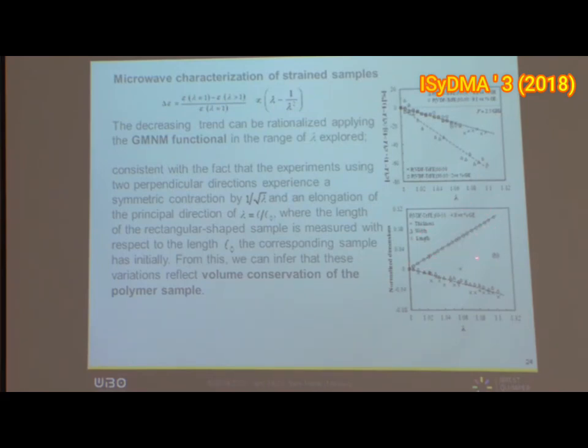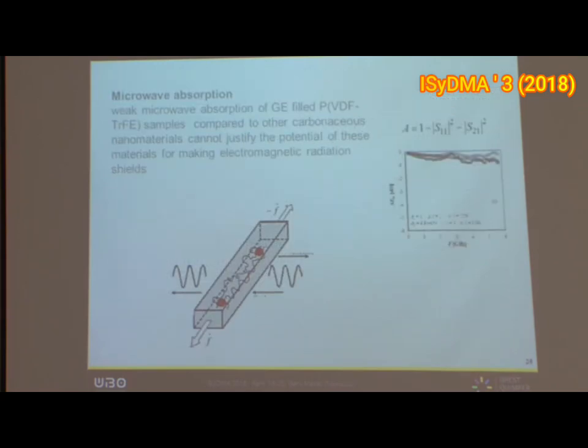The distance in the principal direction varies linearly as lambda, and the two other directions decrease as a function of 1 over the square root of lambda. So if you multiply 1 over square root of lambda by 1 over square root of lambda, multiplied by lambda, you get 1. So the volume is constant. This is proof of principle, a check that the elasticity network is a relevant model to interpret this kind of result.